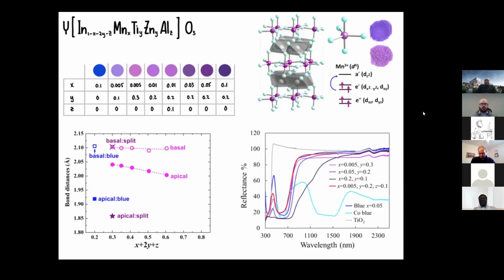What's even more interesting than that, okay, so he had figured out what the origin of that color was, and it was based on that apical distance. But another interesting facet to this is the near infrared reflectance of this, shown on the right-hand side, as you see the reflectance as a function of wavelength, was enormous, which means if you use this as a paint, then it's going to be reflecting heat. So you can imagine painting a roof with this and having a great deal of reflectance. And it's also environmentally stable and environmentally friendly.